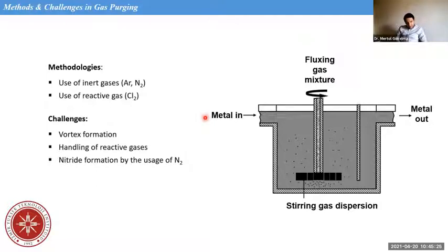So the challenges here are, first, vortex formation, which will increase oxygen. So while removing the dissolved impurities, you form solid impurities. Another challenge is handling of reactive gases. It's not very easy to handle chlorine gas. And another challenge is nitride formation if you use nitrogen as an inert gas. Some companies use that because it is cheaper, but then aluminum nitride is formed, which is a solid impurity and must be removed.